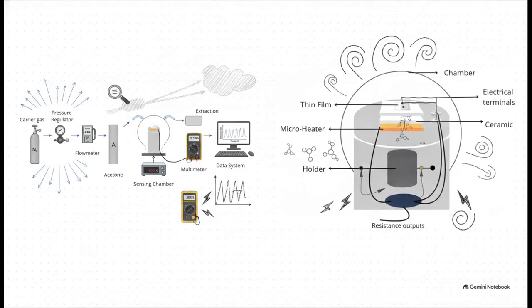After synthesizing the materials, we obviously had to put them through their paces. We used XRD, FTIR, and SEM to really dig into the structural properties of the films. Then came the true functional test, the gas sensing chamber. We used a microheater to precisely hold the operating temperature at 300 degrees Celsius. Under those thermal conditions, we constantly monitored the electrical resistance of the films while hitting them with controlled bursts of acetone, ranging from 1 all the way up to 500 parts per million.